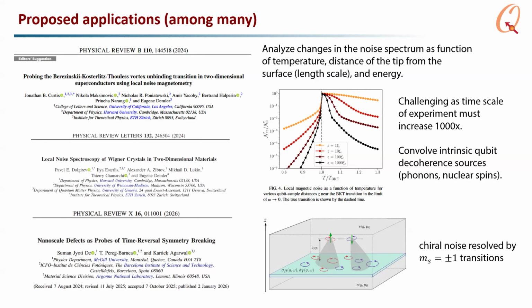But these experiments are very challenging, because if the noise goes from 10 to the -3 to 10 to the -6, it's basically all zero in the experiment. If I really want to tell the difference between 10 to the -3 and 10 to the -6, my experiment has to get 1,000 times longer. And there are other sources of decoherence that these models don't consider, which might be convolved. But it's a worthwhile effort to try to look for these things. So you basically have to vary the temperature, vary the distance of the tip from the surface, which gets you access to different length scales, and maybe vary the energy of the noise that you're sensitive to. That means changing the magnetic field.